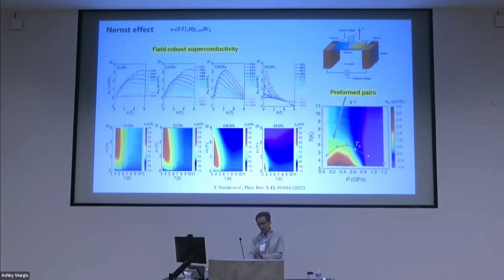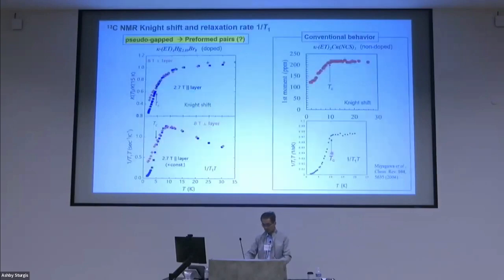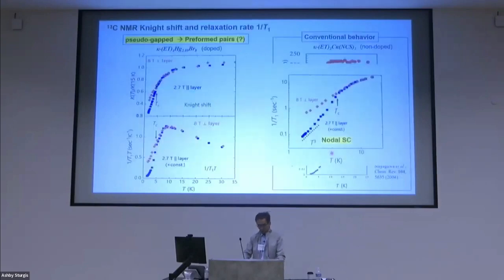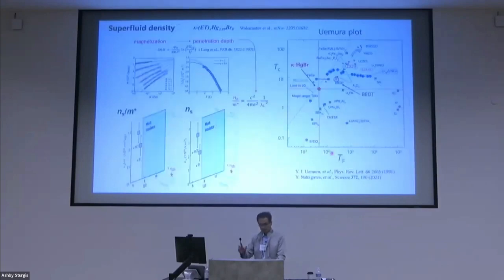At high pressure ranges, the behavior is conventional. In this range, the Nernst signal keeps strong even at higher temperatures. In these regions, the superconductivity is very robust to magnetic field. This is consistent with the BEC picture for the pairing. Okay, and I'd like to show you the superfluid density.